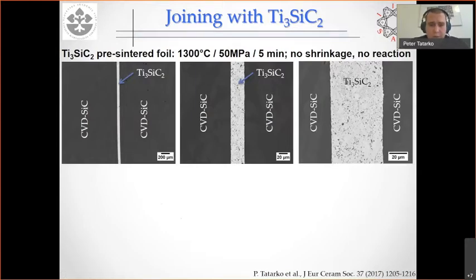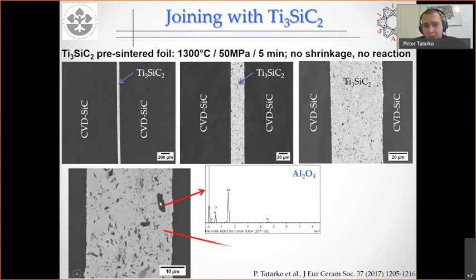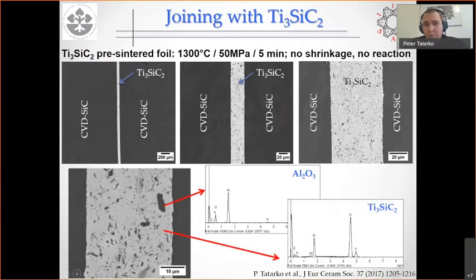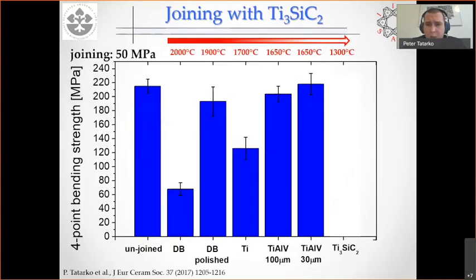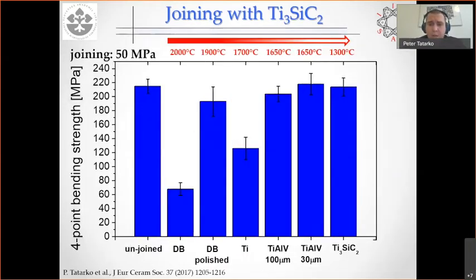If we zoomed in, we only found the alumina particles, which we wanted to be there, and the remainder was just the titanium silicon carbide. So from how the joint looked on the inside in the SEM, we were quite happy with that. And then let's have a look at how the joint mechanically performed. You can see here that with the titanium silicon carbide, we got almost the same strength again as we obtained for the unjoined material.